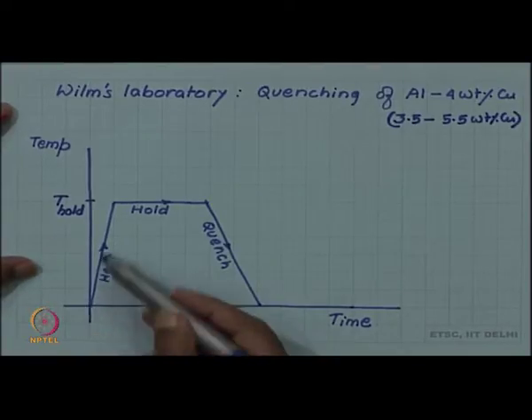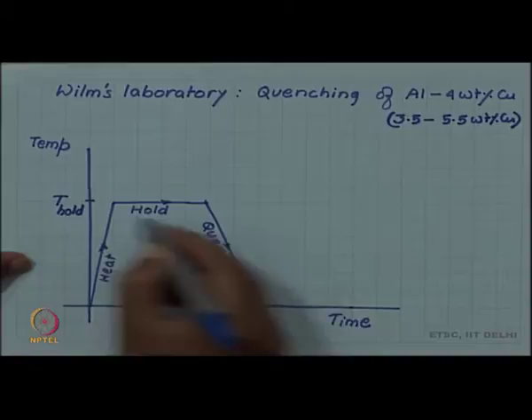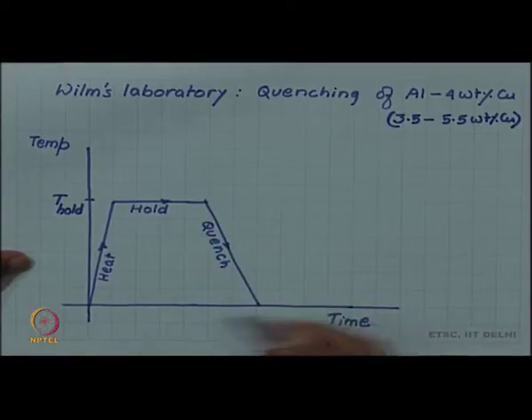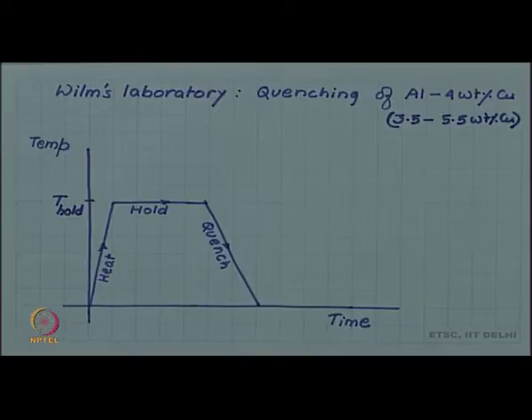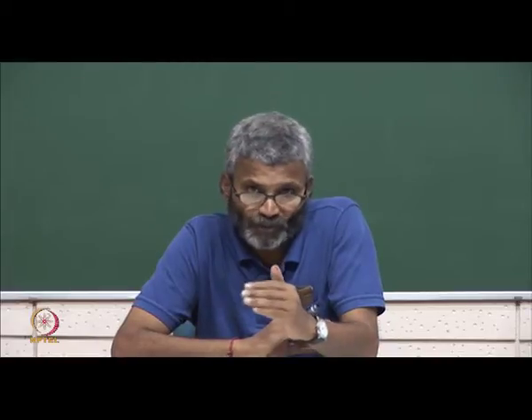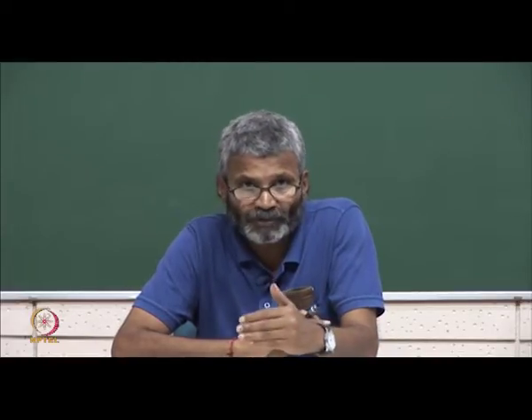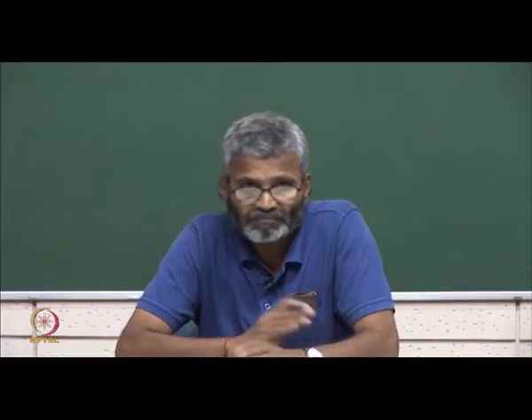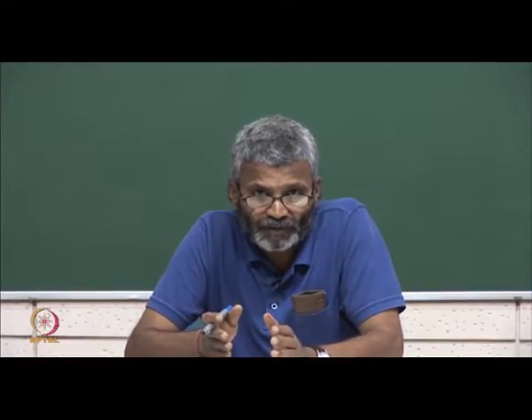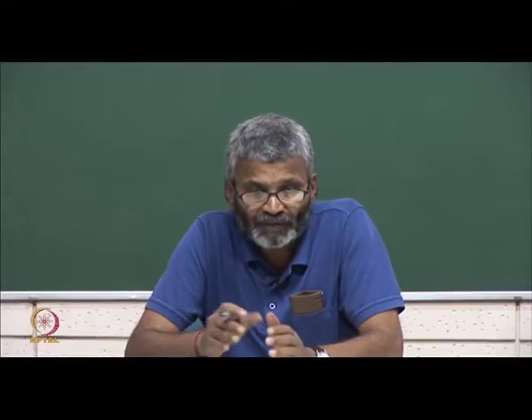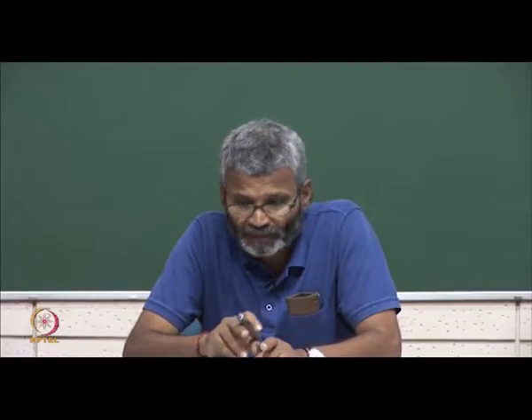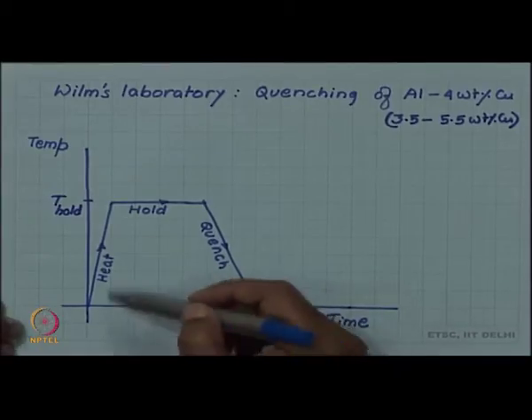He had several variables in his hand. At what temperature do you hold, and at what rate do you quench? We know from the steel example that if we do not go to the temperature range in which the austenite phase is stable, and we take it only below the eutectoid temperature and then quench, it's not going to have an effect. You will not have austenite to begin with, and there will be no martensite forming. So thus, if you want to form martensite, you have to heat it above the austenite temperature.